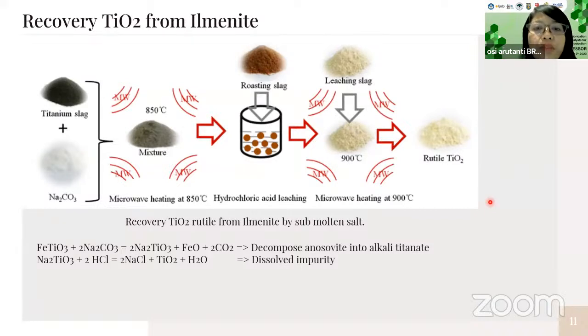What is the difference from the conventional method? Here, they use sodium carbonate and ilmenite, and then they use a microwave process to reduce the temperature and time of the process. By this process, it can be found that both the time and temperature of the process can be decreased more.